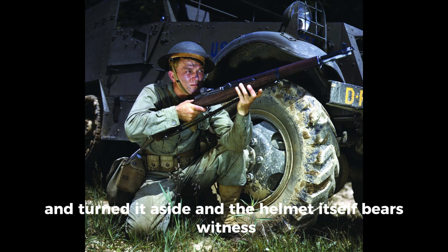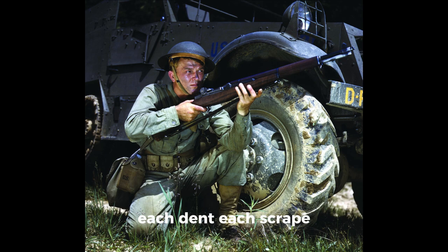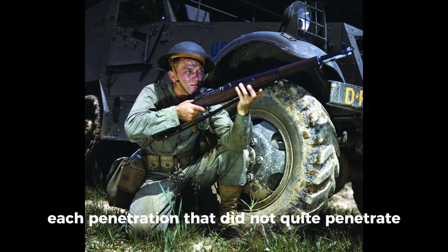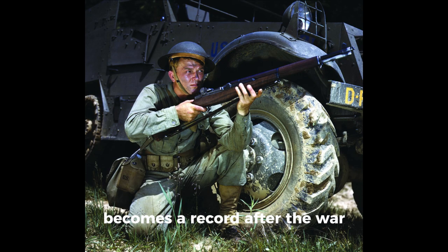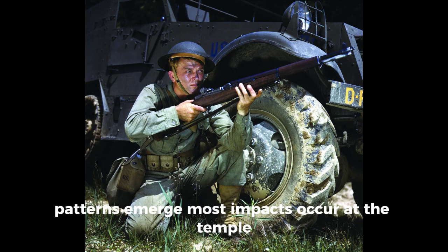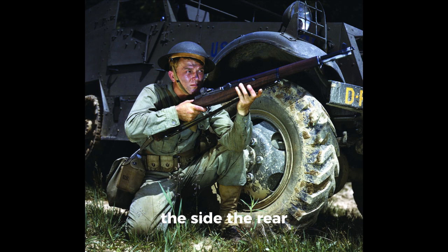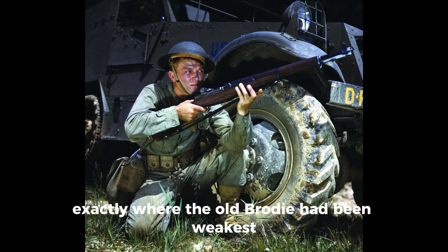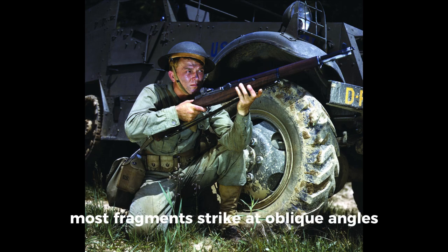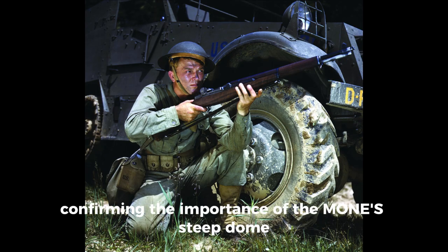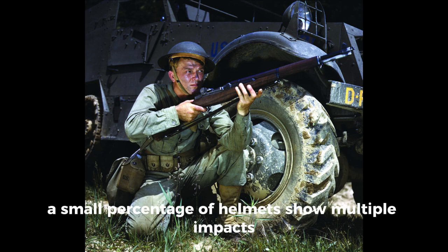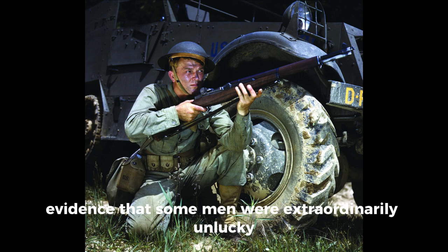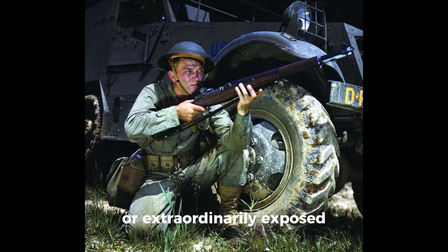And the helmet itself bears witness. Each dent, each scrape, each penetration that did not quite penetrate becomes a record. After the war, helmets are collected, catalogued, studied. Patterns emerge. Most impacts occur at the temple, the side, the rear, exactly where the old Brody had been weakest. Most fragments strike at oblique angles, confirming the importance of the M1's steep dome. A small percentage of helmets show multiple impacts, evidence that some men were extraordinarily unlucky or extraordinarily exposed.